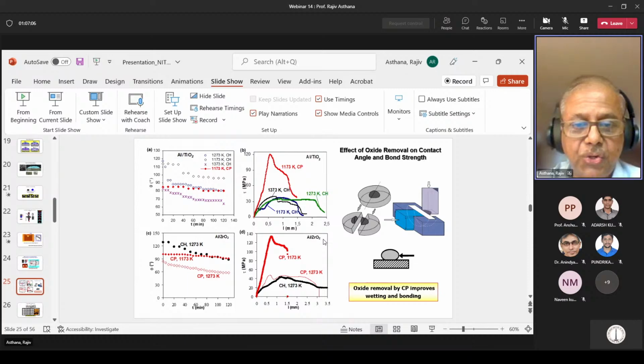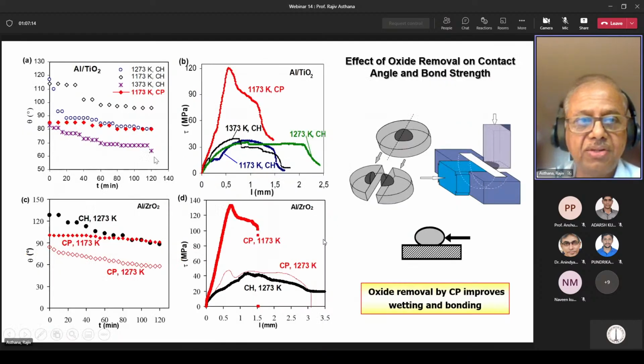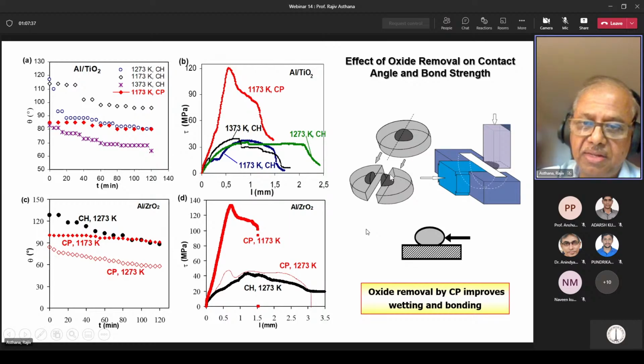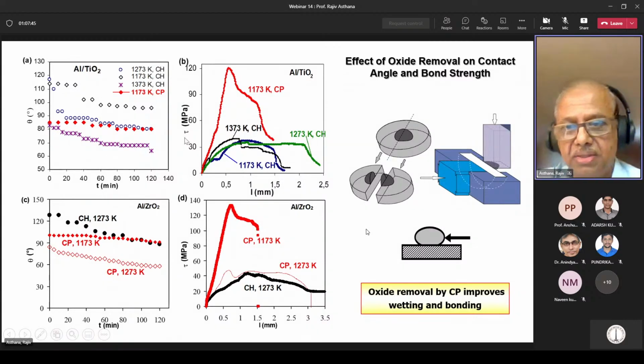And these are some data that show what happens to the bond strength of the joint in a system like that. So we are looking at aluminum droplets on titania substrates, and we looked at experiments where we had capillary purification process and also contact heating process. So for these two types of sessile drop test, we let the test run, then solidified the droplet, and then we bisected the droplet assembly and did shear tests. Based on those, we estimated the shear strength or bond strength.